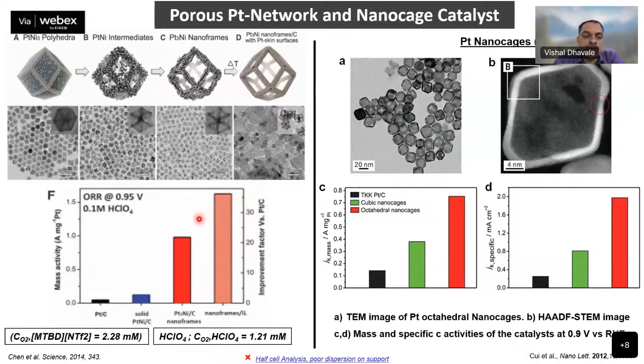This performance was tested and reported over here at a very onset potential where the oxygen reduction reaction starts. That's a kinetic region over here. With that kinetic region itself at close to 0.95 volt, where the OCV is close to around 1 volt for the practical fuel cell, and we are starting at 0.95 potential, just the initiation of the oxygen reduction takes place, and you can see the improvement in the activity is almost more than 30%. So it has beneficial advantages of such kind of electrocatalyst in the fuel cell activity compared to the state of the art Pt/C catalyst.